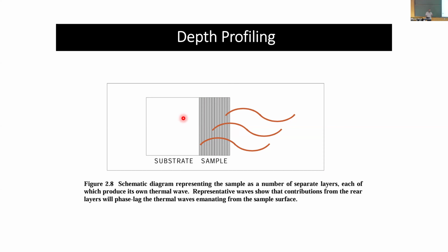But if you can precisely place the absorbing layer at different depths and do a systematic study, you can actually do a depth profile using PDS in a systematic way. And such a depth profile is not possible with any standard technique.